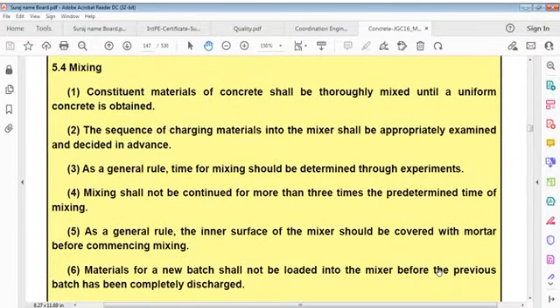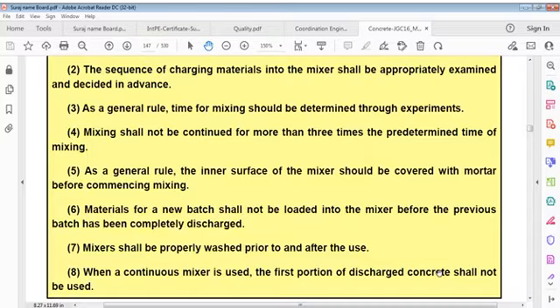Mixing. Constituent materials of concrete shall be thoroughly mixed until a uniform concrete is obtained. Sequence of charging materials into mixer shall be appropriately examined and decided in advance. As a general rule, time for mixing should be determined through experiments. Mixing shall not be continued for more than 3 times predetermined time of mixing.